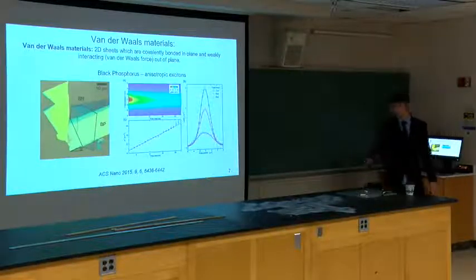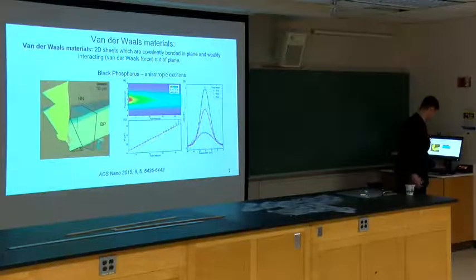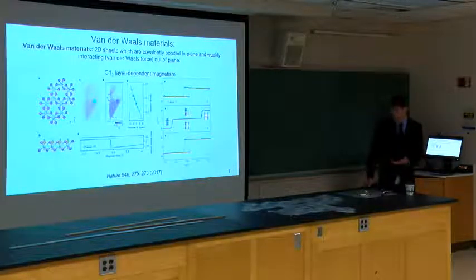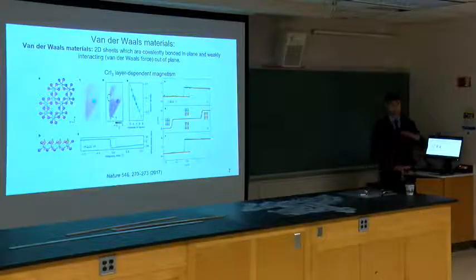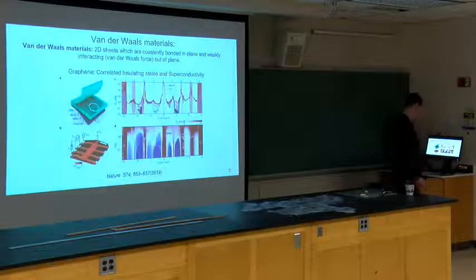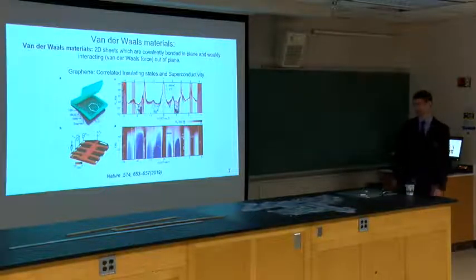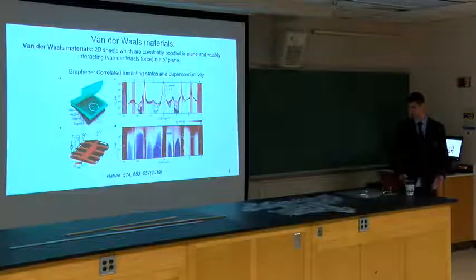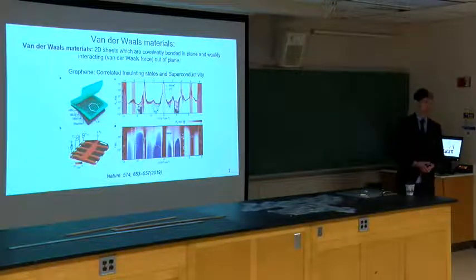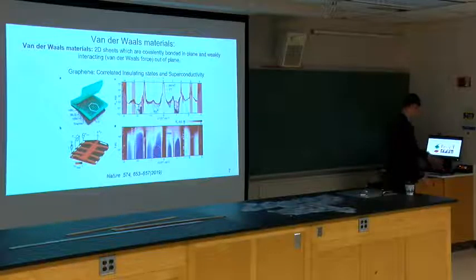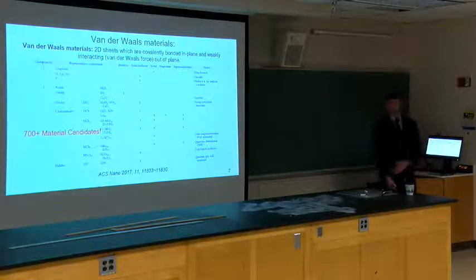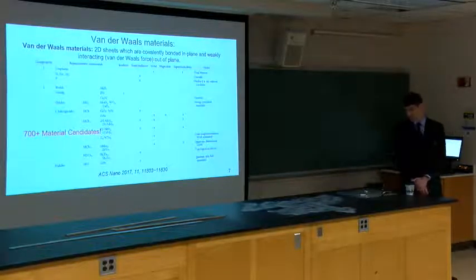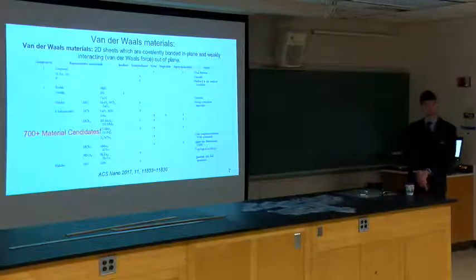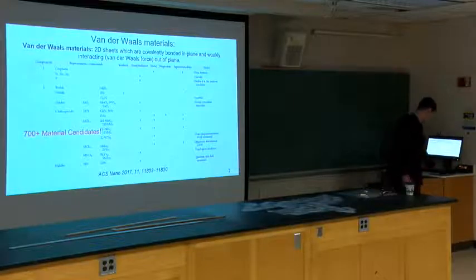So this is one example with anisotropic excitons in black phosphorus. We have layer-dependent magnetism due to variations in the exchange interaction, depending on how many layers you have and the stackings. You can have superconductivity. I'm sure everybody has heard of this. If you twist two different layers of graphene with specific angles, you get flat bands, and you can induce strong electronic correlations. There's a lot of candidate materials. Right now, the best number I've been able to find is 700. I think that's probably an extremely low count of what the actual number of materials is. So we have a lot of room to play.